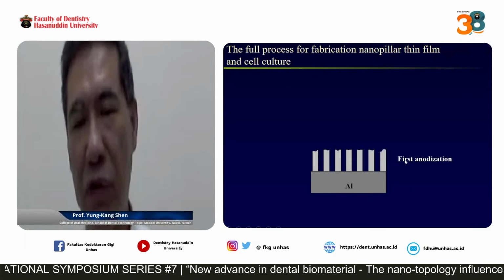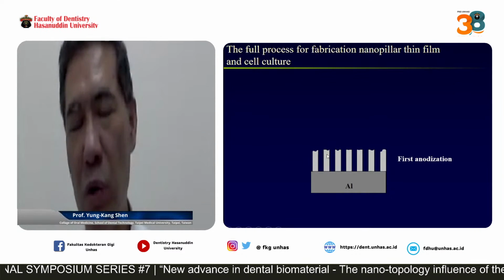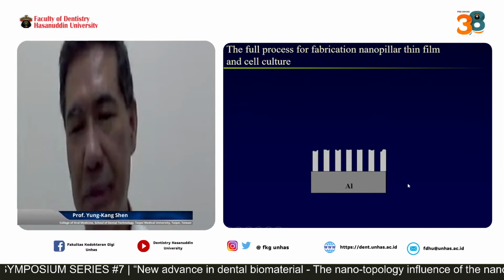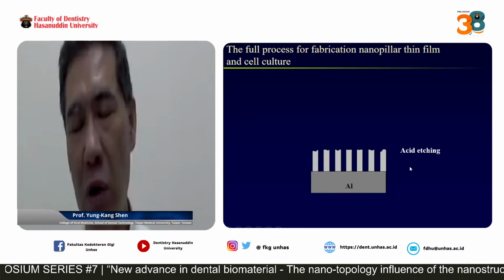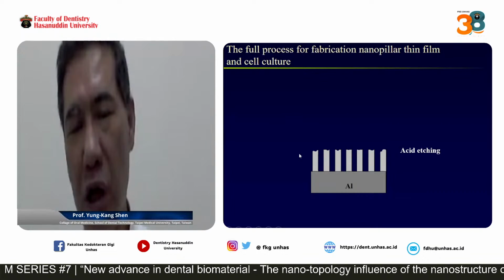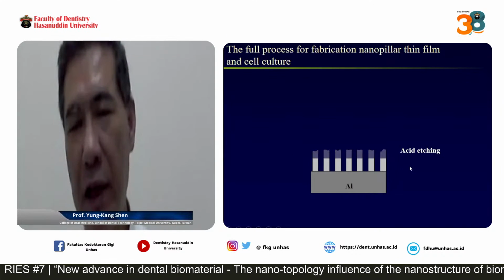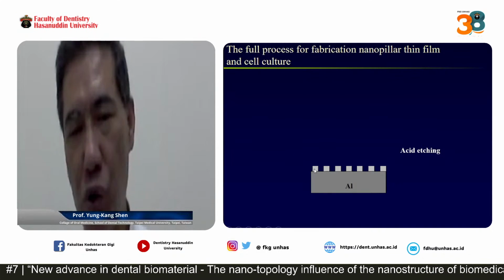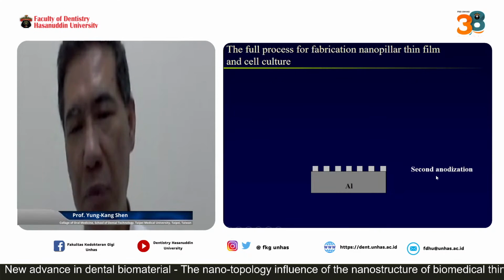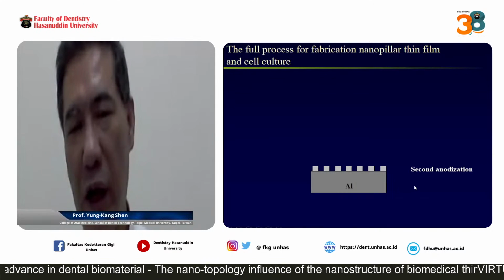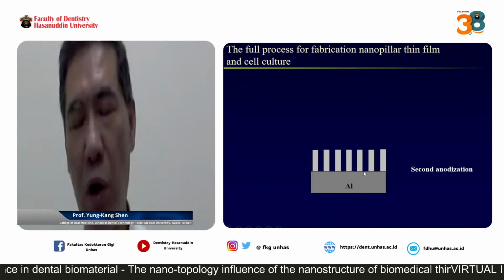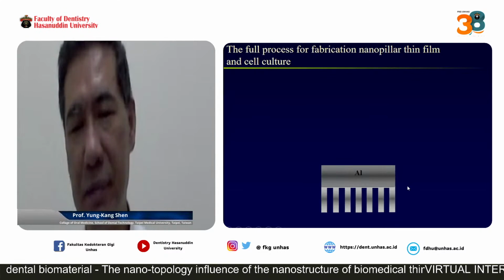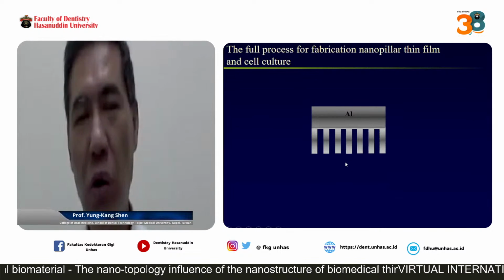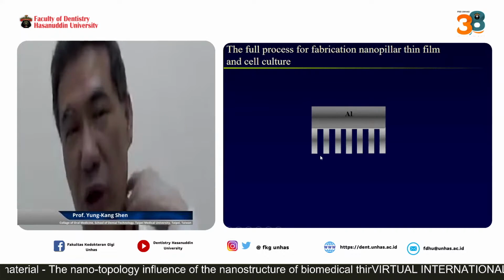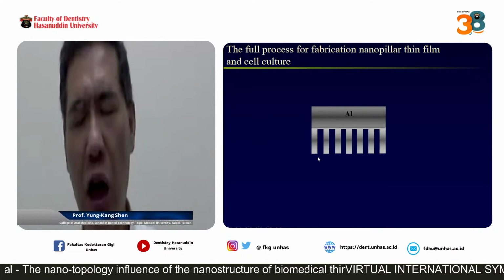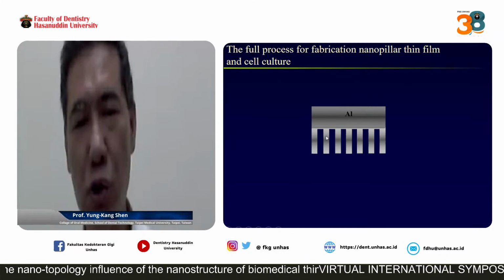Then we do the first anodization on the aluminum tablet, and we get an irregular nanostructure on the aluminum tablet. And we use liquid to do the etching, to etch the nanostructure here. You can see we can etch to get a very short nanostructure. And we do the anodization again, so we can create a second anodization to get a very good and very regular nanostructure here. Now we can get this tablet. We can call it the AAO, anodized aluminum oxide. So we can get many nanostructures here.